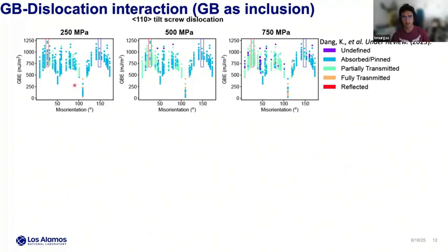You can see that as we apply a higher stress, from 250, 500, 750, you have more fully transmitted or partially transmitted dislocations. So this complicates the problem a little bit more. It means that we have to consider metastable states also, and the dependency on the stress and on the misorientation angle.